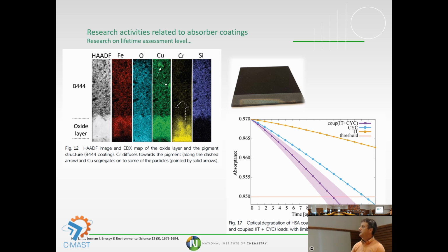So you can see here an image of the coating. We cut a small piece. Here below is the substrate made of Inconel. Then on the Inconel, an oxide layer is formed, just of chromium oxide. This chromium oxide is often used as a protecting layer, and then those elements are diffusing inside the coating. So you see here the porous coating. Imagine that a high amount of binder is sometimes evaporated, sometimes burnt out. So it's really difficult to produce a dense coating for such a high temperature.